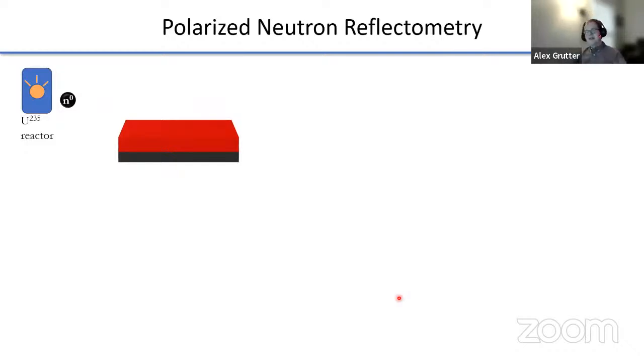Okay, so with all of that background, we have finally arrived at what I actually do, which is polarized neutron reflectometry. Polarized neutron reflectometry is a depth-sensitive probe. So basically, if you have a thin film heterostructure and you want to know which layer is magnetized, that's what neutron reflectometry tells you. And in fact, this is exactly what you want for a study of magnetic proximity effects. So in principle, it's extremely simple. You take your neutron, you throw it at a sample, and our main requirement is the sample be shiny so that it's nice and reflective.